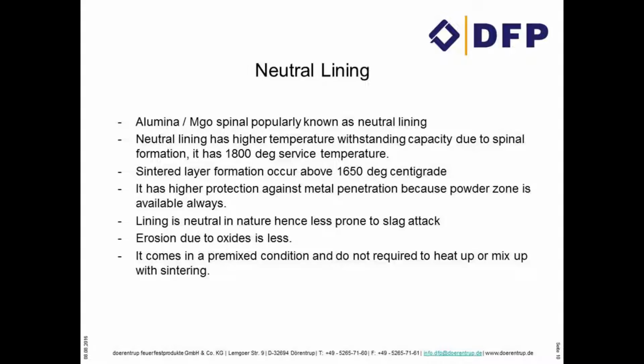Lining is neutral in nature, so it has very little slag attack. And the erosion of the lining is basically due to either the slag or the temperature. It has a 1800 degrees centigrade working or service temperature and is neutral in nature, so the erosion because of the slag as well as the temperature is very less. It comes in premix condition and does not require any heat up or mixing up with sintering.